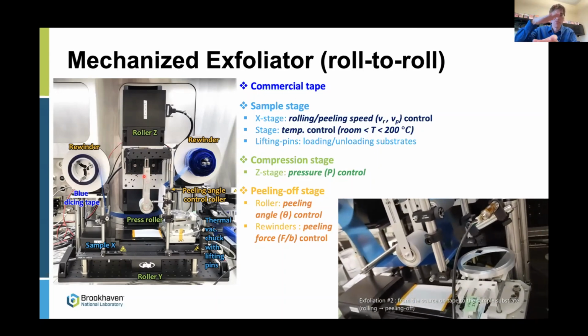And we can press down while we move the substrate back and forth. And that simulates the same behavior as if a human was doing this tape-to-tape thing, where they're pressing it together. And it transfers some of those flakes onto the substrate, between the substrate and the tape. So you can do two steps. You can transfer from the graphite onto the tape and then bring in a clean substrate and transfer from the tape onto the clean substrate.